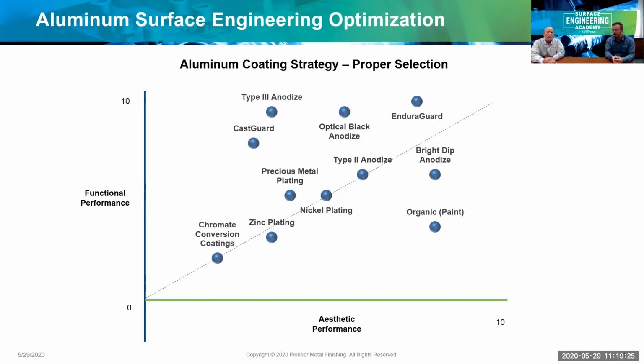Walk us through, Steve, some of the characteristics here in the chart, knowing that you have functional up the y-axis and aesthetic performance up the x-axis. Yep. Well, as you can see on the functional side of it, we've noted type 3 anodizing. Type 3 anodizing can produce a coating that has wear resistance equal to 70 Rockwell steel. So that's a great coating for wear resistance. We've also got the CastGuard that I alluded to, where we can allow our customers to save costs by casting the part and now produce high corrosion resistance on a casting.